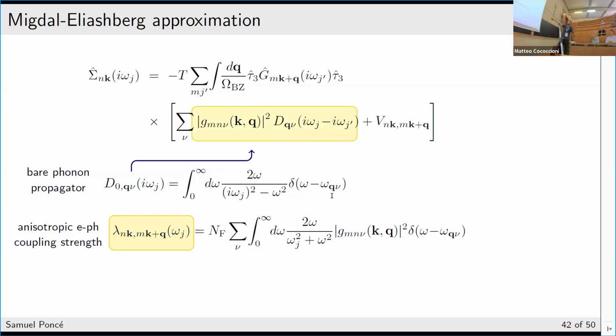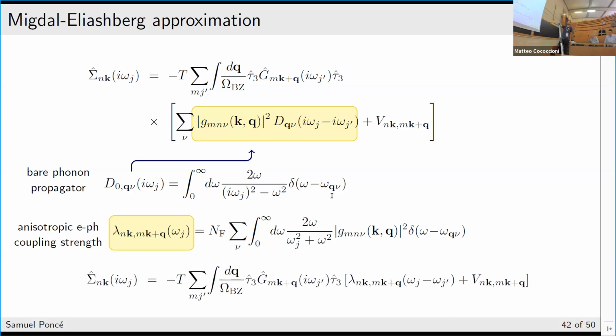So one can do some approximations now. If we want to compute this, instead of the full phonon propagator, we can use the bare phonon propagator. That's a much simpler expression. And also, just to simplify the equation, we can define an anisotropic electron-phonon coupling. This is a generalization of the lambda that you saw in the McMillan-Allen-Dynes theory. Now you have this lambda, but it's resolved in both electron and phonon momentum. And you see that we have this term here. If we do this, you can have a somewhat simpler expression. You have the Green's function, then you have this anisotropic coupling strength, and then again you have this electron-electron term.